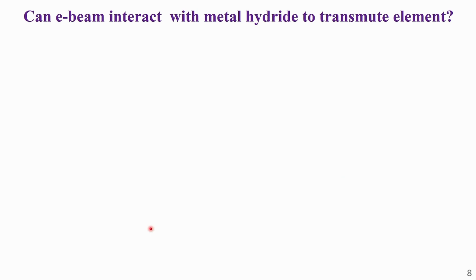Can an electron beam interact with metal hydride to transmute elements? In our experimental study, we use EDS, which uses an electron beam of energy 20 keV, to check for transmutation products in the electrode sample. We want to make sure that the transmutation products observed are not formed due to interaction of the electron beam with the electrode sample.